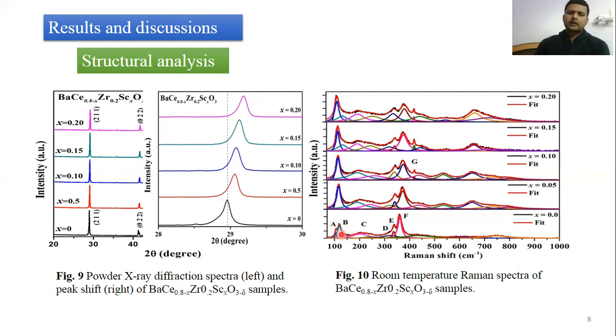Here we can observe that the two peaks are weakened to one, and thereby showing that the short range symmetry of the lattice has increased. Thus, both XRD and Raman spectra reveal that the sample being prepared is chemically stable.